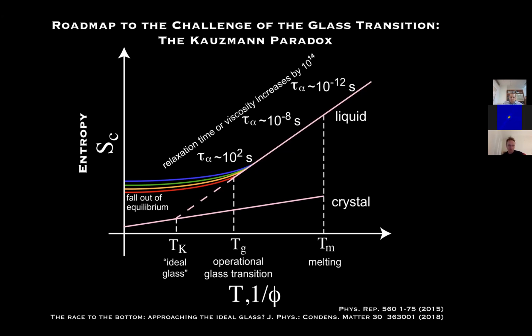Now, from a thermodynamic perspective, precisely nothing happens at this temperature. However, 100 seconds for the relaxation time is long enough in the lab that we don't wait much longer, and so we say the material has fallen out of equilibrium. And so the rainbow colored lines refer to the material falling out of equilibrium, and so the entropy drop no longer follows this straight line that it would do if it were in equilibrium. But if we could somehow drop the temperature very slowly, the dashed extension of the pink line, it would intersect the entropy of the crystal. And this leads us to one of the great paradoxes of the glass transition problem. Because if that were true, we would have a liquid whose entropy was the same as that of a crystal. And that is a very strange idea, that suddenly we have this disordered state which has the same entropy as the ordered crystal.